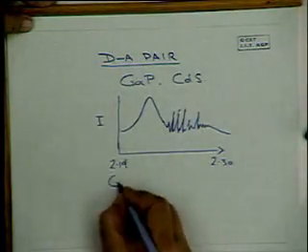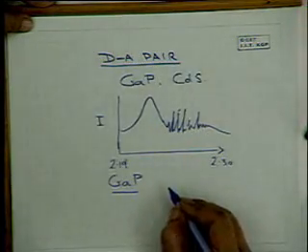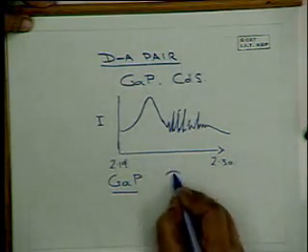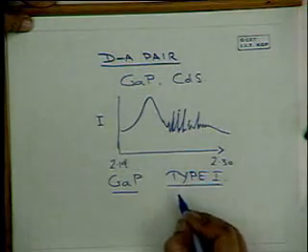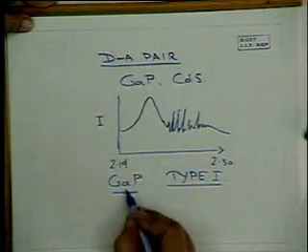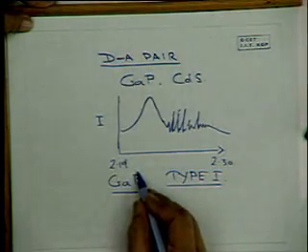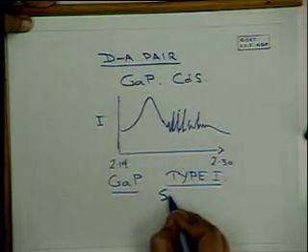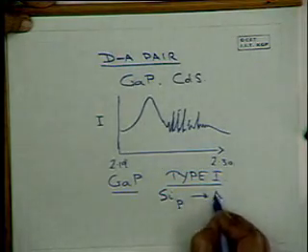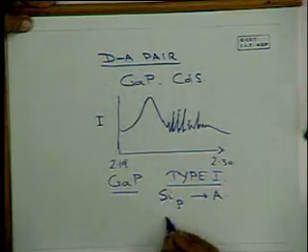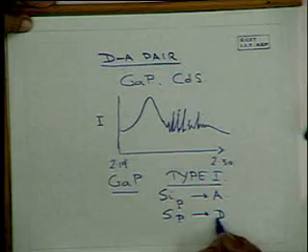say in gallium phosphide, we can have two types of donor-acceptor pair recombination. For example, in type 1, we can have the donors and acceptors both sitting on the phosphorus site. What is a typical case? We can have silicon sitting on phosphorus site, group 4. This is an acceptor. And we can have, say, sulfur sitting on phosphorus site. This is a donor. Right?